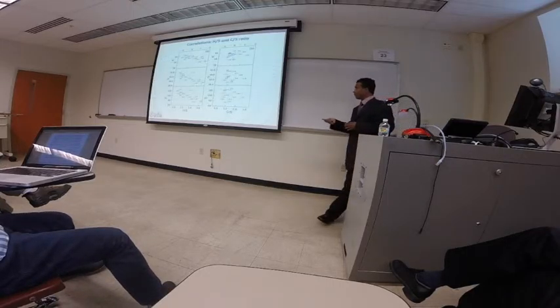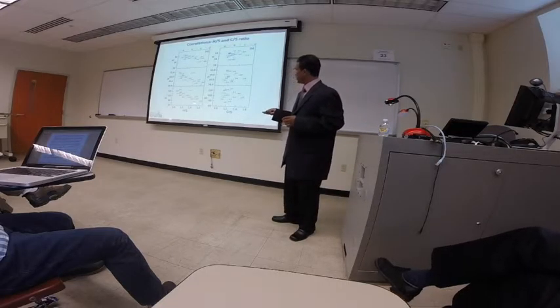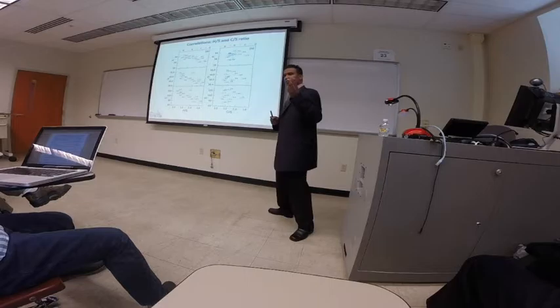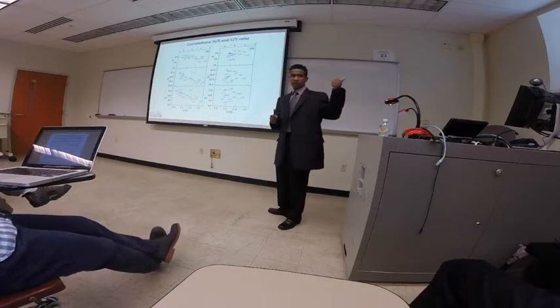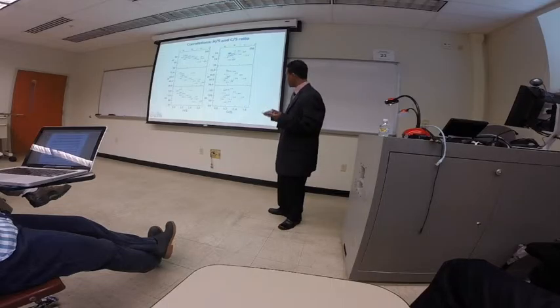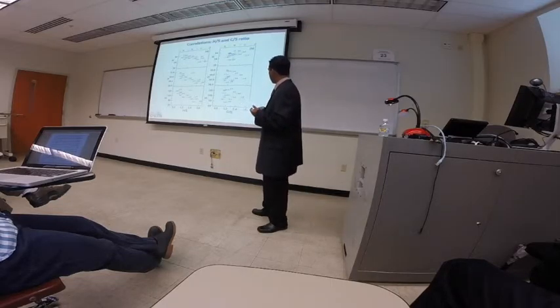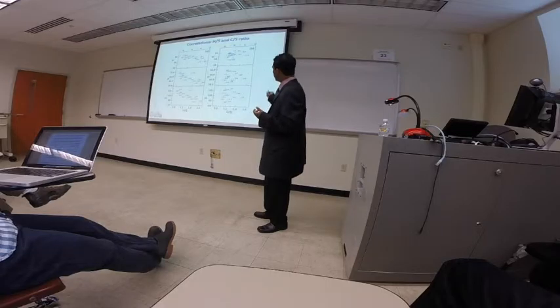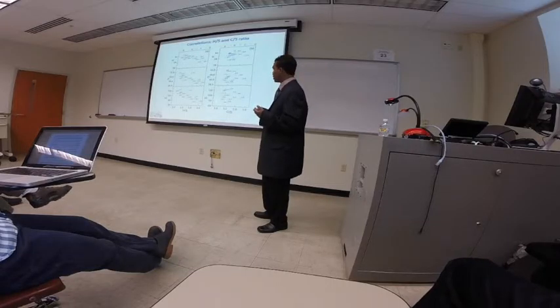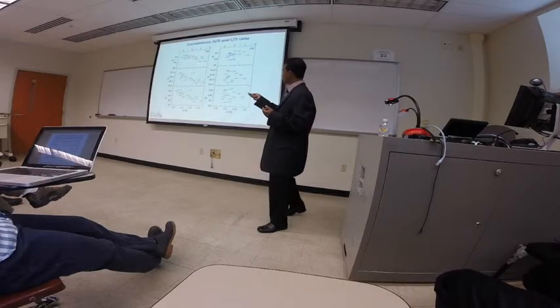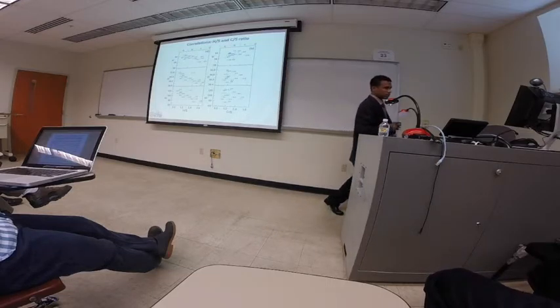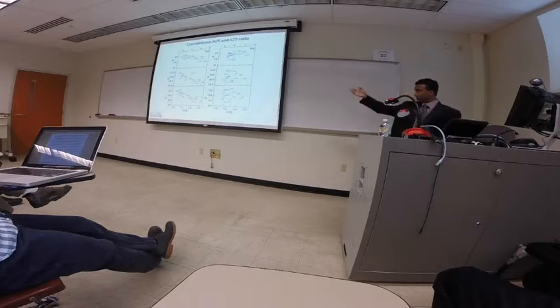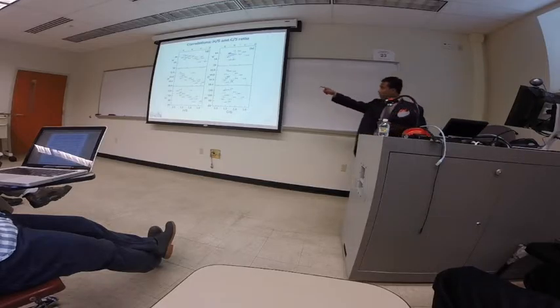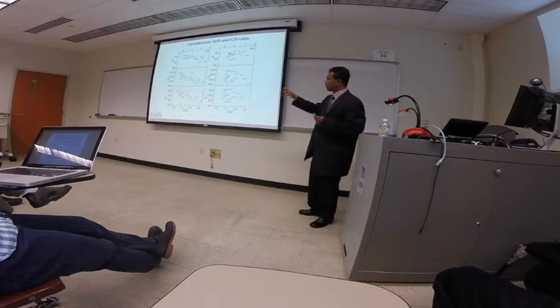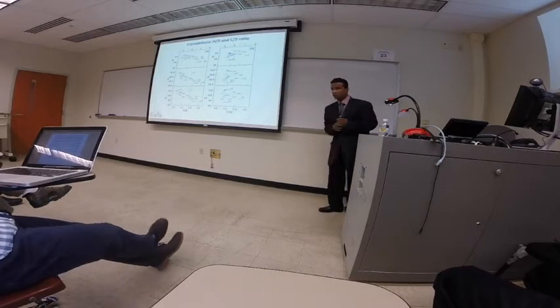Then we figured we should find the relationship between the molar ratios as well. Why? You have CSH, three things. So you can have C/S ratio, H/S ratio, or S/C ratio. S/C ratio didn't give us anything, but we found that C/S ratio actually is a very poor characterization metric in terms of mechanical properties. There's no correlation whatsoever. But H/S ratio has an inverse correlation, at least within the sample we considered, with the mechanical properties. And also there's only 3 bulk mechanical properties. We found that Poisson's ratio actually is not correlated with any molar ratio.